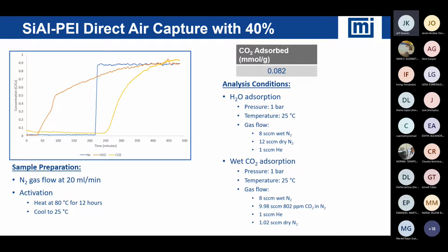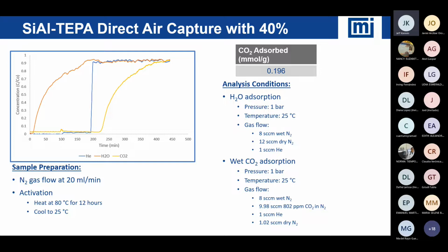If we change the type of amine, right? So we go to a different amine, much more significant adsorption can be obtained in that same 40% relative humidity stream. So now we're looking at an improvement of effectively 8x. So by adding the simple amine, we could triple it. By changing the amine, we can now go 8x. And you notice the performance now starts to be very similar to the microporous materials, but in the presence of water. So really significant now that we can do the multi-component analysis and start to truly understand materials and gain better insight into the materials.